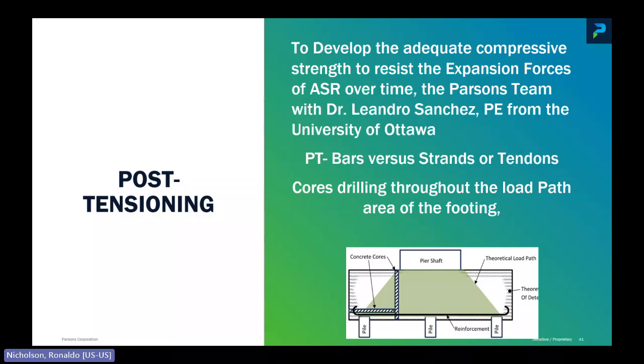And finally, it was the post-tensioning. We decided to go with PT bars versus strand tendons for providing the post-tensioning. We felt this was more, again, constructible and more readily monitored than going with tendons or strands over the long run. Those cores that the post-tension bars would go through would be another challenge, given the huge dimensions of the footings. As previously shown, the cores can be very extensive, and they had to basically be able to support the straight bars once they were completed.